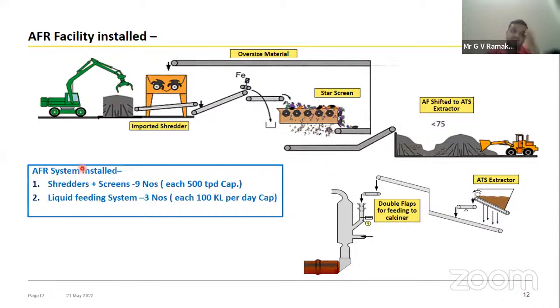In Dalmia Cements, we have installed around 9 shredders and screens, with 500 tons per day capacity. Our present consumption is around 3,000 to 4,000 tons of plastic, RDF, and hazardous materials per day in our cement kilns at around 8 locations. In liquid feeding systems, we have installed 3, which consume around 100 KL, 100 tons per day of capacity. This is the quantum of waste we consume in our cement industry, which helps the community by reducing the dump area where the huge stock of RDF or biomined RDF was stored.